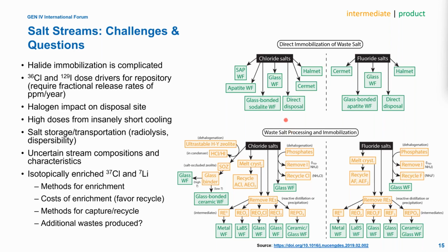And then when you start thinking about partitioning, this plot is a very high level summary, and it's missing lots and lots of things that could be done. But it gives you somewhat of a flavor of options where you could take these salts and you could react them with things. One of the processes I'll talk about later is where you react it with an ultrastable HY zeolite. The hydrogen in this zeolite reacts with the salt to generate hydrogen chloride, which can be removed and recovered, and then your remaining product can be consolidated. You've got options of salt-occluded zeolite where you add a binder and you can yield a glass-bonded ceramic waste form or a sodalite, glass-bonded sodalite.